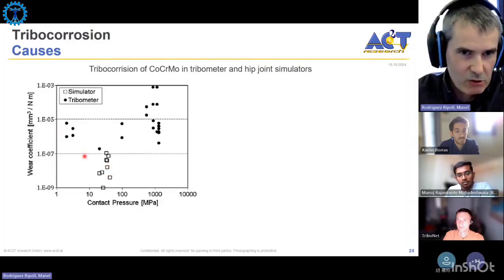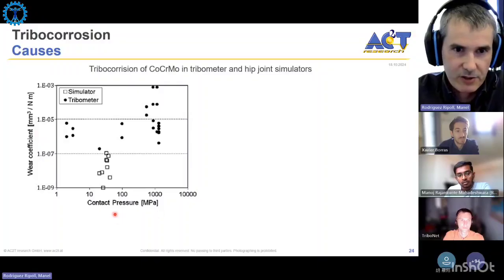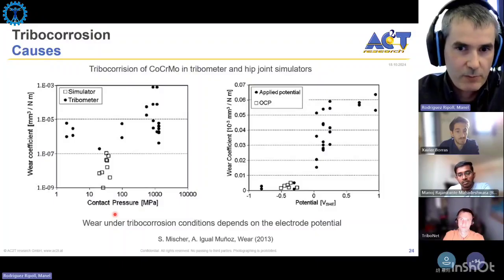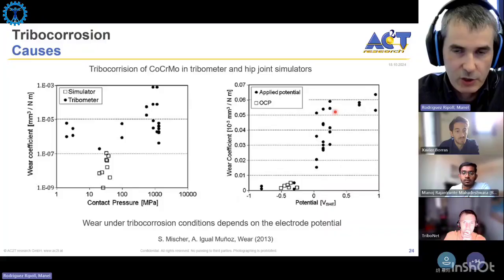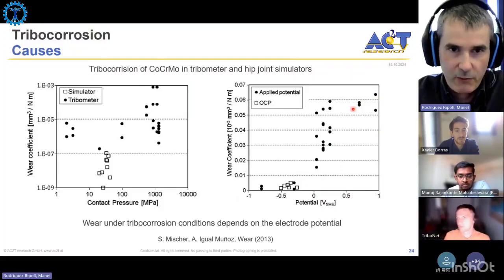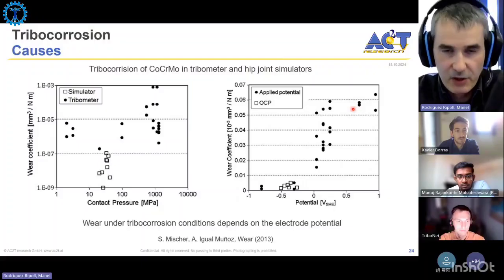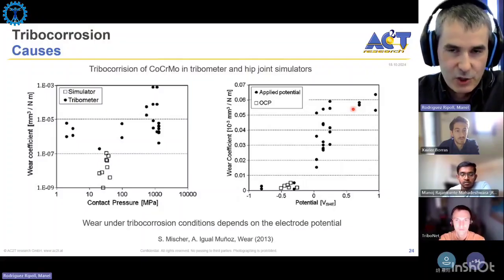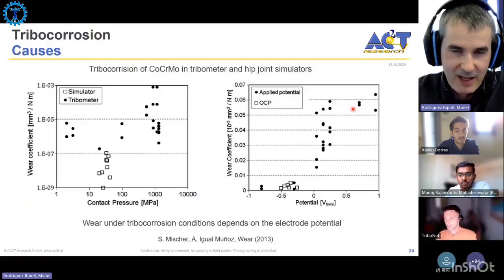So basically, this data looks really difficult to interpret if you plot the wear coefficient as a function of the contact pressure. But if you plot the same data as a function of the electrode potential, then all this data collapses into a master curve. And this is what I was mentioning before. Under cathodic applied potentials, the wear is the lowest in tribocorrosion, and as you increase the voltage and go into the passive domain, when you have an applied passive potential, is where you have this most destructive synergy between wear and corrosion, because you are triggering the formation of a passive layer with increasing potential, even a thicker layer. And of course, if you mechanically destroy this passive layer in this continuous process of building and destroying, at the end you will have the most dangerous synergy and the highest wear in this process.